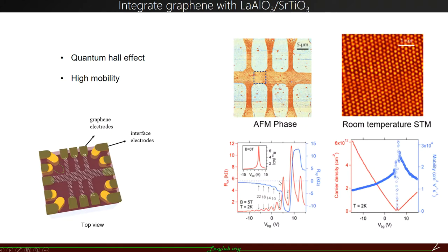And here is the transport measurement done at 2 Kelvin. We can see the quantized plateaus of graphene at 2, 6, 10, etc. The mobility of graphene can be as high as 30,000 at 2 Kelvin.